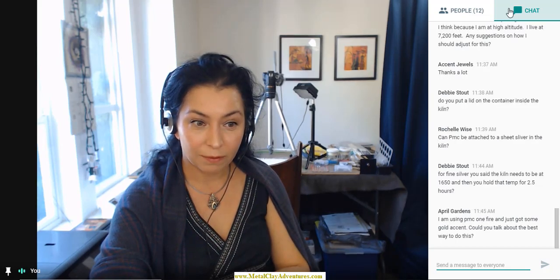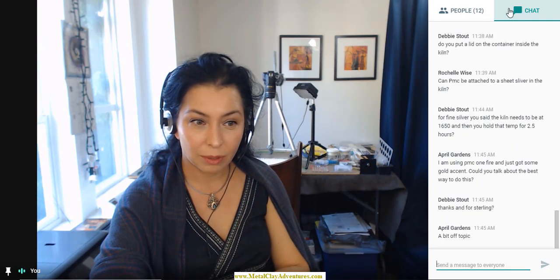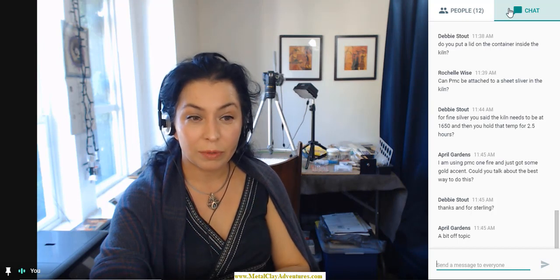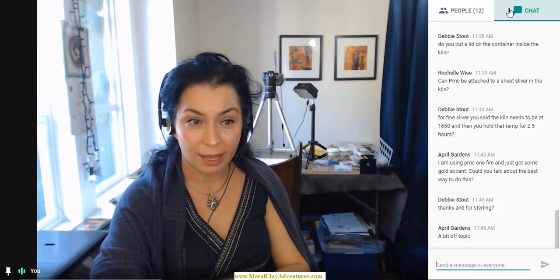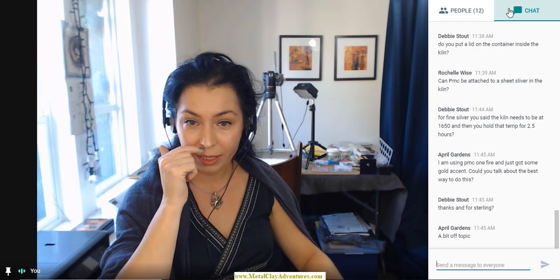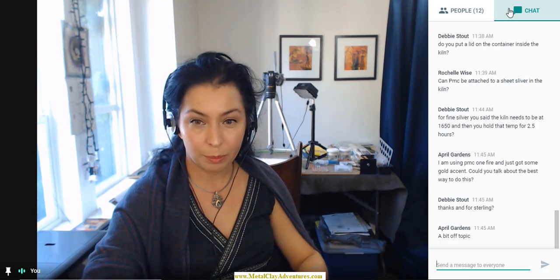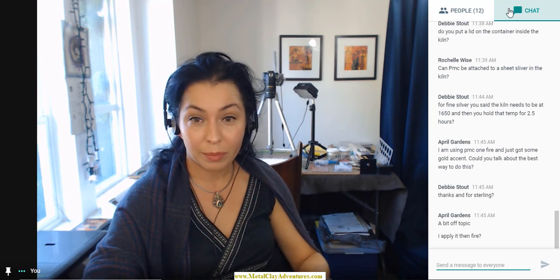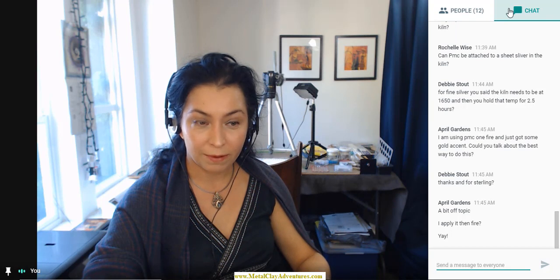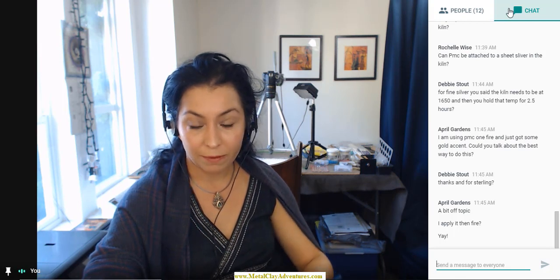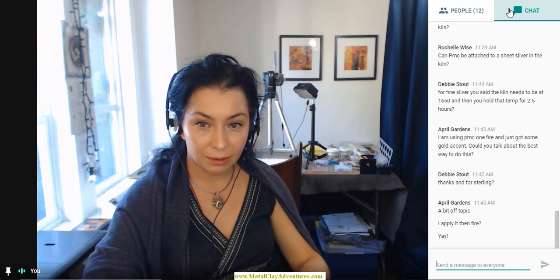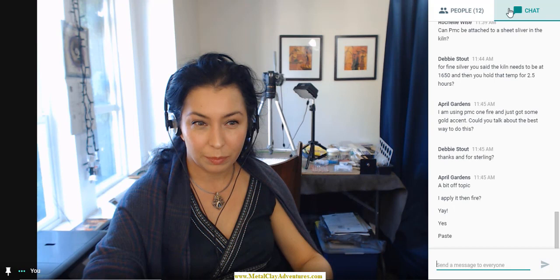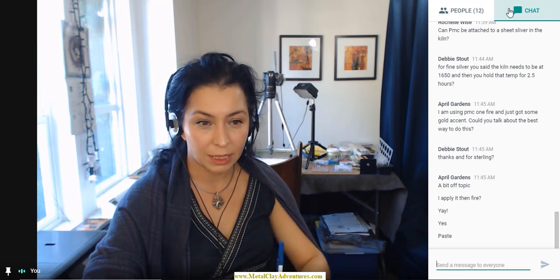April, I'm using PMC1 fire and just got some gold accent. Could you talk about the best way to do this? April, you don't need to do anything on PMC1 fire if you want to apply gold. Just apply on it. It will work perfectly. If you want to be very precautious about it, you'll need to gild deplete before applying the gold, but I am not. I found that PMC1 fire works without gild depleting. So fire the metal and after add the gold, the paste. Did you get the paste or the foil? Add the paste or the foil and proceed with kiln firing or with torch firing and sintering it.